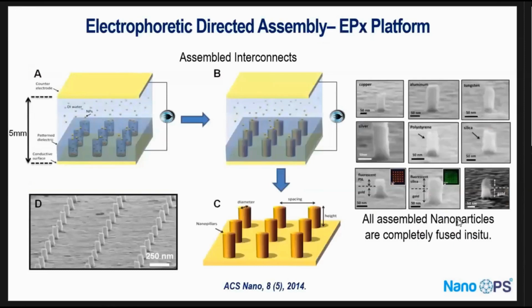We call it the electrophoretic assembly, directed assembly platform. And this one takes, for a 4-inch wafer, less than a minute. And here you can see these are gold, for example. Basically you will have vias made in whatever material you have, whether it's a polymer, silicon dioxide, whatever it is that you're using, high K. And then you do the assembly.